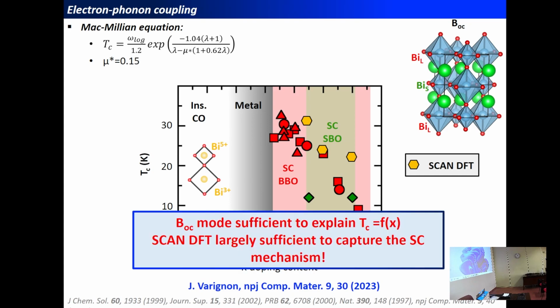And therefore, in these systems, just considering one single phonon mode, which is intimately, strongly coupled to the electronic structure, is sufficient to reproduce the evolution of the critical temperature as a function of the doping content that is observed experimentally for this system. And therefore, the SCAN functional appears to be largely sufficient to capture the superconducting mechanism of these systems. So with this study on the bismutates, we have been able to identify what are the degrees of freedom we have to incorporate and understand the superconducting mechanism of these systems.